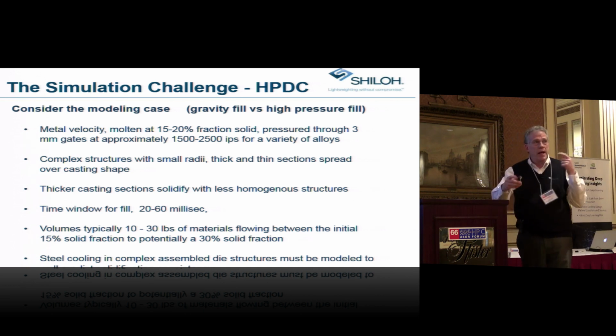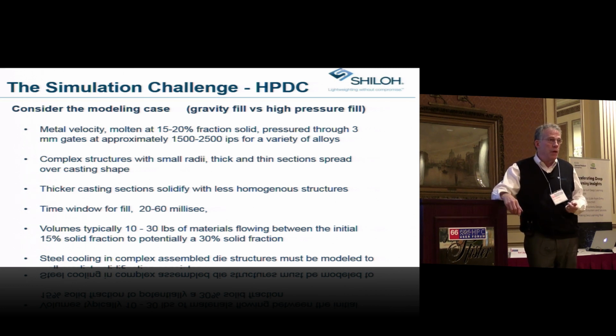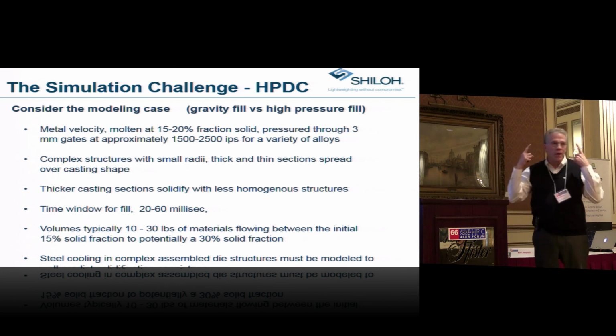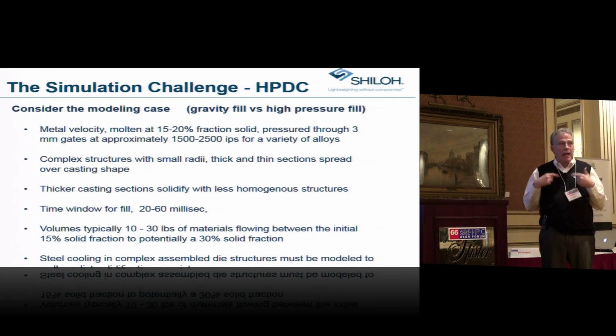And then, if we can model the cooling effectively, we can reduce the dendritic structure even smaller, because the dendrites are a function of cooling speed. And we end up getting 10 or 15% greater properties in the same kind of geometric shapes. So if you put the hat on of the engineer saying, okay, how am I going to get more properties out of less material? This is the path that I need to be taking.